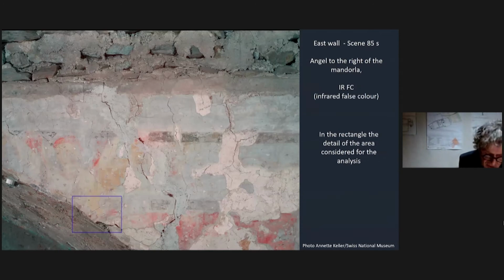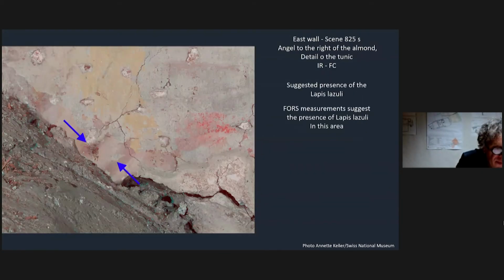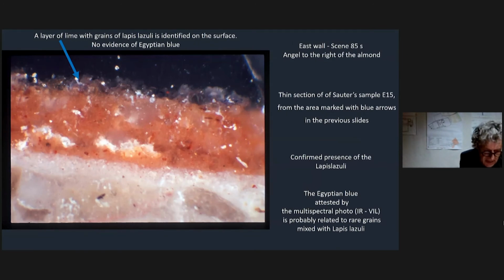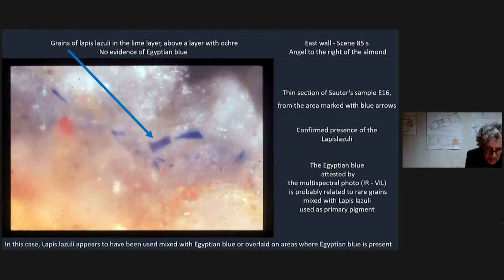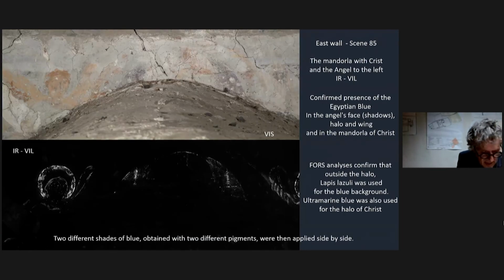The images with IR fluorescence confirm the presence of Egyptian blue, and in the shadows of the robe, analyses indicate the presence of Egyptian blue and lapis lazuli used together. This is also confirmed by the cross-section of a sample taken from this area. In this case, the Egyptian blue is probably related to rare or smaller grains mixed with lapis lazuli used as the primary pigment. In the same scene is therefore testified the use of two different shades of blue obtained with two different pigments, applied side by side.